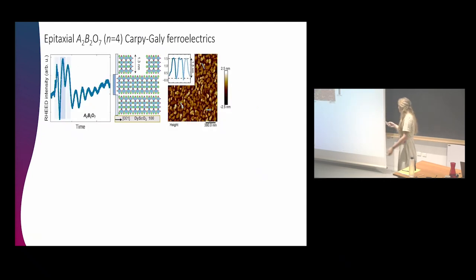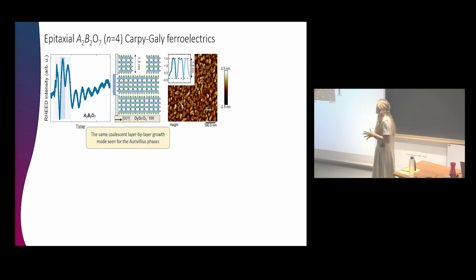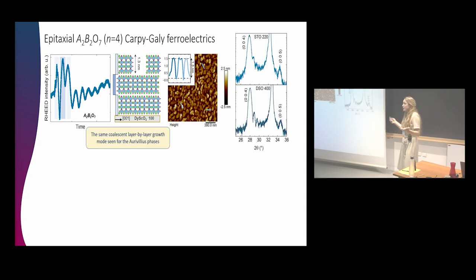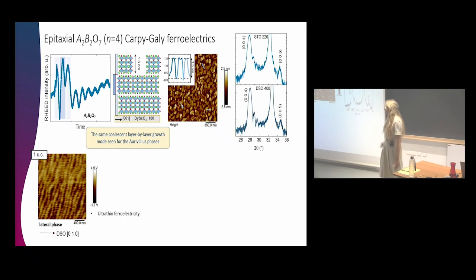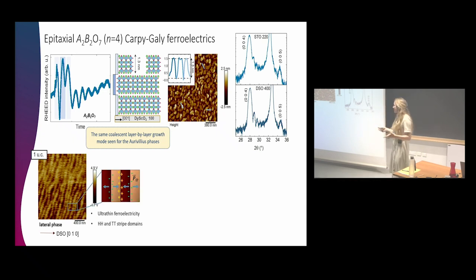And then again, I went through the same film optimization, and we actually end up with a very similar story to what I showed you for the Aurivillius films. So it looks quite consistent through different families. So we could again get these big RHEED oscillations, stabilize nice layer by layer ferroelectric growth with all the islands being exactly half, or in this case, 1 unit cell in height. And even grow it on different substrates. Interestingly, we could still see the same stripe domains at 1 unit cell, so we have the same ultrathin ferroelectricity, same head-to-head, tail-to-tail stripe domains, so it's very nicely reproducible for different families as well.